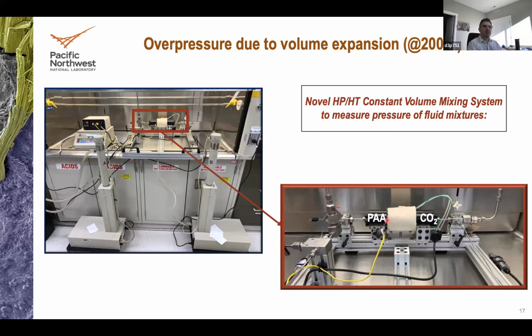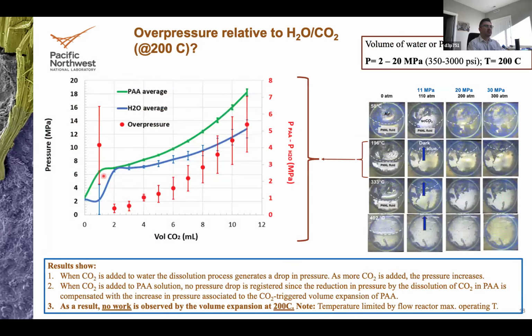And polymer solution. So most of the cell is filled with polymer, and then we add a milliliter of CO2. At 6 megapascal, we close the valve, and what we see is that in the case of water, the 6 megapascal goes down to 2 megapascal. This is understandable because when you add CO2 in water at these pressures, we have a dissolution process that will generate a pressure drop, okay? In the case of polymer solution with CO2, we add at 6 megapascal, we close the valve, we let it react, and it stays at 6, 6.5 megapascals, okay?